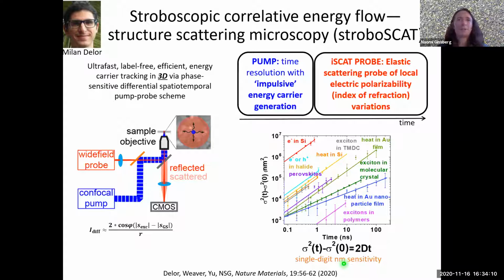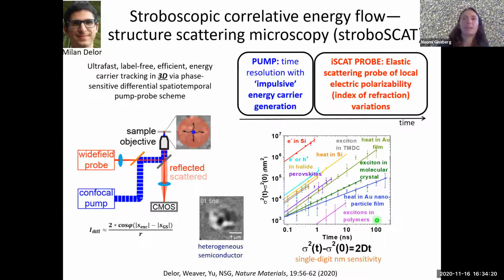But especially on a log-log plot like this, it can be really easy to hide effects of heterogeneity that are patently on display, for example, in this data series here, which is an example from a heterogeneous semiconductor. And so the real lesson of this story that I'll emphasize is that when you have heterogeneous materials, diffusivity is a bulk parameter that may or may not reflect what's actually happening in the intrinsic properties of the material.